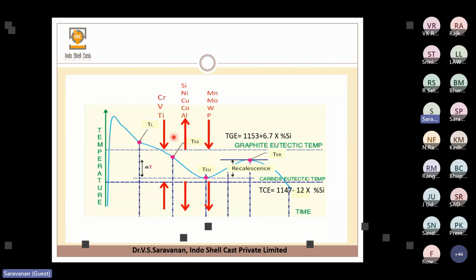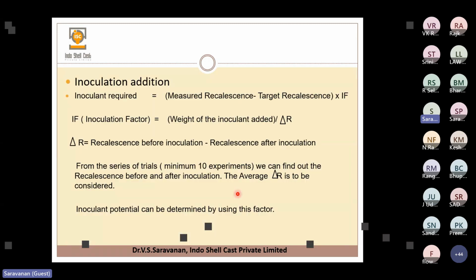Based on that we get the microstructure, mechanical properties, all those things. So where the TEU is present, and what these boundaries are, based on that all the properties of the metal are derived, and the software tells all those things. Here, for the inoculation addition, as I told you earlier, we can adjust the inoculation percentage based on the recalescence. For example, the inoculation required is the measured recalescence minus the target recalescence, times the inoculation factor.